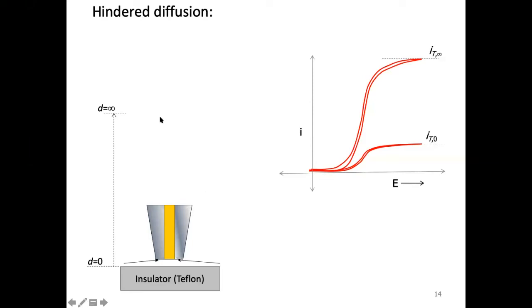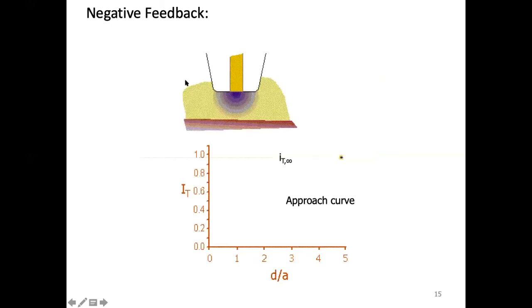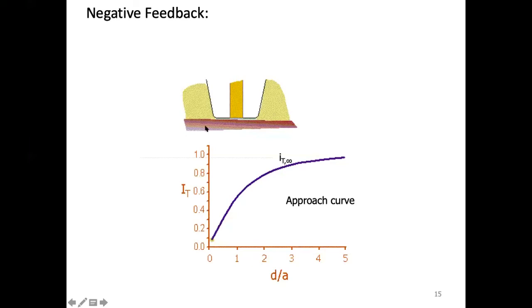So I am measuring the tip current as a function of distance from the substrate. If you do this process continuously, as shown in this illustration, the SECM probe, shown here on the top, is approaching the insulating substrate. The gold part, this yellow part, is basically the electrode, and the contours you see are the hemispherical diffusion. In the lower illustration, tip current is plotted versus the distance between the substrate and the tip.